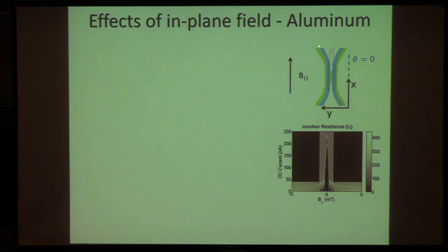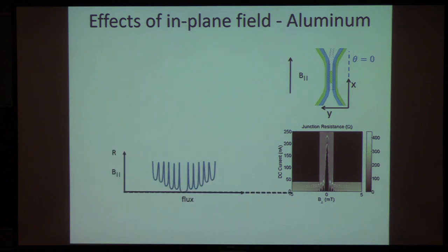So here's a schematic of this junction. There's one superconductor, another one, and in the middle here we have our semiconductor. Dimensions here are a few microns along the junction and a few hundred nanometers across. And here you can see what normally you would find when you apply a magnetic field perpendicular to a Josephson junction, and that's a Fraunhofer pattern. This is a very canonical type of pattern where the critical current shown here in this envelope is oscillating as a function of flux. And this is a magnetic field now applied perpendicular to the junction just as a means to characterize what the junction is doing. So this is going to be a very weak field on the order of a few millitesla. The big parameter that's going to change the physics is when we apply a large magnetic field on a scale of a Tesla in the plane. So remember, just to distinguish, this is a weak probing field, and the relevant parameter will be the one applied in plane, parallel here.